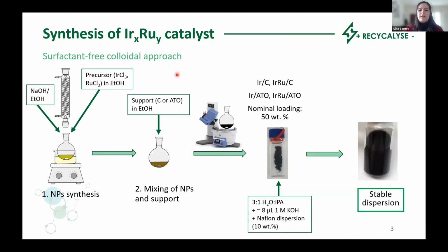And as mentioned before by Christian, we are using iridium and ruthenium, as these are the state-of-the-art metals for the oxygen evolution reaction. The synthesis follows a surfactant-free colloidal approach, where the dissolved precursor salts are mixed with alkaline ethanol and heated under reflux. Once the metallic nanoparticles are formed, they are mixed with the support, either carbon or antimony-doped tin oxide, ATO in short.